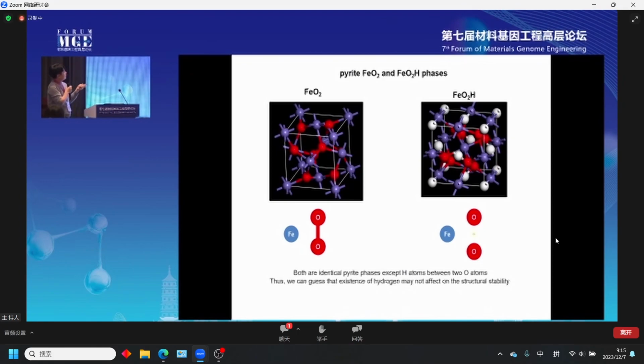So FeO2 has this O-O bonding, and this iron has equivalent distance to these two oxygen atoms. And when it comes to the hydride, it has a hydrogen here, located exactly in the middle of these two oxygen. So it has a very symmetric position here. The only difference between these two is the existence of this hydrogen position in the middle of two oxygen.